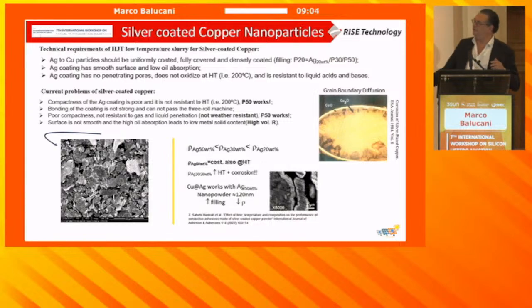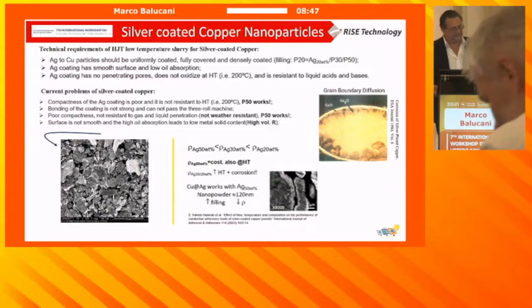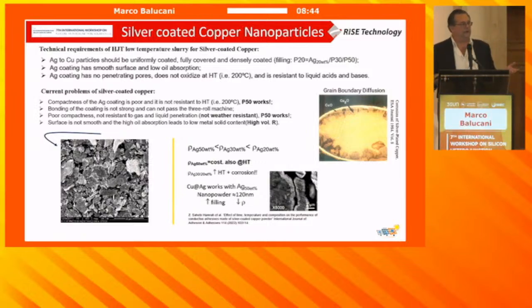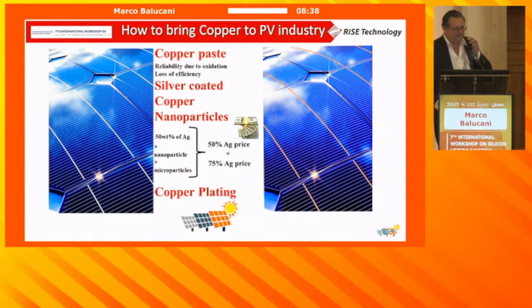Moreover, you have to consider that for heterojunction, you're using not balls, but flakes. So it's even more complicated to cover it with silver. You can see here, you can have it not well covered, and there immediately oxygen will oxidize and make a red plaque. So it works well, but we have to see the reliability in time for the silver paste. So let's look at how we can bring copper to photovoltaics. Copper paste, exactly, I recall the Fraunhofer presentation just before, they're working, they have some reliability, they say that they can make it work, but we still don't have stability.